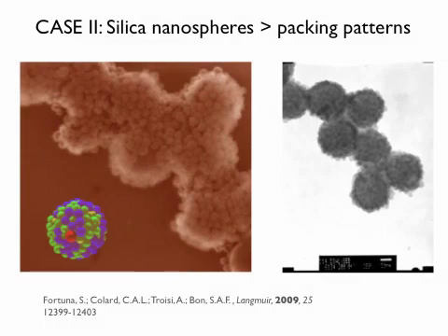Okay, so obviously it's a nice story. You can do this with a range of different materials, right? Here, I think we've seen this slide before in the introduction. Here you have silica particles around tiny little droplets. In this case, we solidified the droplets in order to be able to do conventional SEM and TEM. On the left, you see conventional SEM, unsputtered and on a silicon wafer, and on the right, you see a transmission electron microscopy image. And what you see is that you have these armored raspberry type of structures.